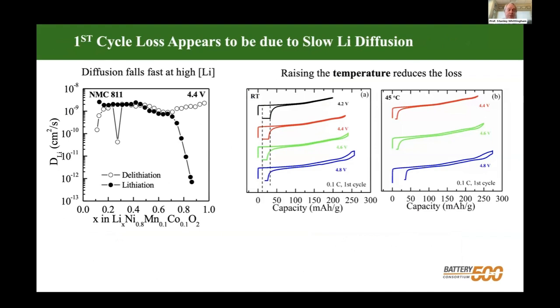So we looked at measuring the diffusion coefficient in these materials, and the black circles here show you lithium going into the 80% nickel. And you can see the diffusion coefficient falls off a cliff after about 70, 75% occupancy. And this can be related to the diffusion mechanism, which is a divacancy mechanism. So you need 2 vacancies, and these fall off obviously very rapidly as you fill the lattice. And this can be compared with if you're giving a lecture in person and the lecture hall is 80% full. The only empty seats are single seats somewhere in the middle. So everybody has to move to allow somebody else to come in. Taking the lithium out, we do not have the same problem. So fast charging is much easier. It's only in the last little bit that we lose diffusion.